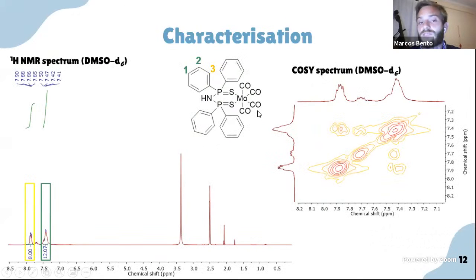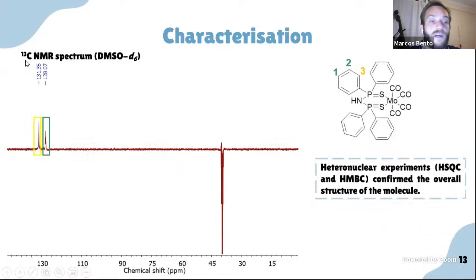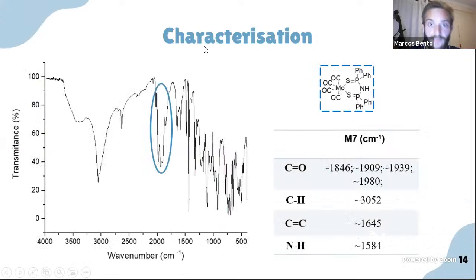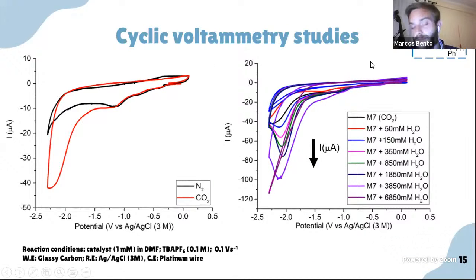So I will start to show you the NMR characterization, and we did some proton NMR experiments, COSY experiments, carbon NMR experiments, and the heteronuclear experiments that led us to confirm the overall structure of the molecule. The FTIR characterization was very important to observe the vibrational mode of the carbonyl ligands bound to the metal. And after all this characterization, we did some cyclic voltammetry studies.